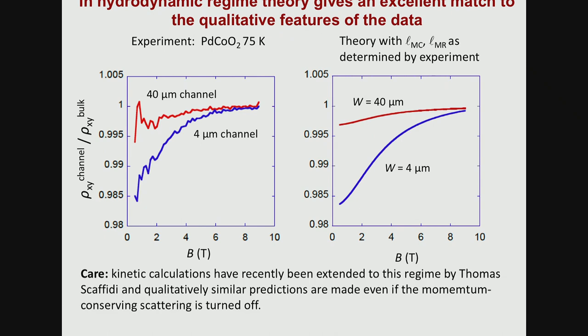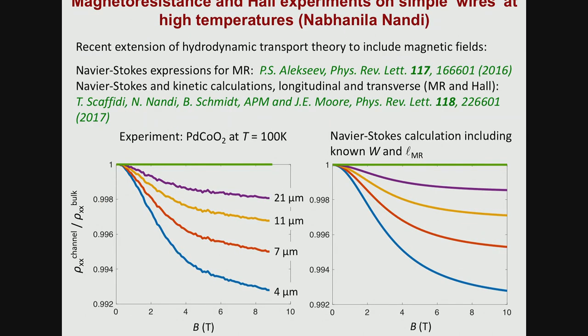To my knowledge, the only way you can do that is with kinetic calculations. They're very hard to do numerically in these geometries and in these range of parameters. Finally, Thomas got it going, and it had a very annoying result because it showed that you can completely turn off the viscous effect. You'll change the numbers a bit, but you don't change the fundamental shapes of either this or your predicted magnetoresistance. So that's actually quite depressing, because that says that you can do experiments that, if you want to be optimistic, might be hydrodynamics, these field experiments, but you can't say they definitely are, and that's, of course, what everybody would like to do.